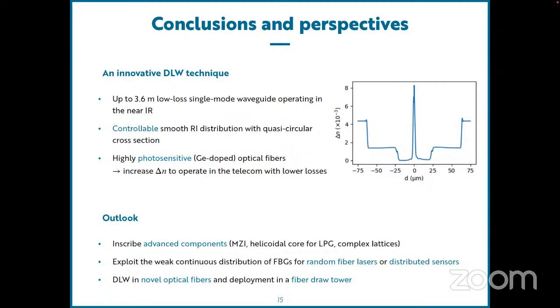The work in progress concerns highly photosensitive optical fibers that are doped with germanium. So the goal is to increase the refractive index to operate in the telecom with lower losses. So we can see here on the right some results, and with a germanium doped optical fiber, you see that the refractive index is highly enhanced. In this case, we still have a lot of losses, so we have to find some tricks and some annealing procedure to remove or decrease the natural losses. And this is a work in progress.